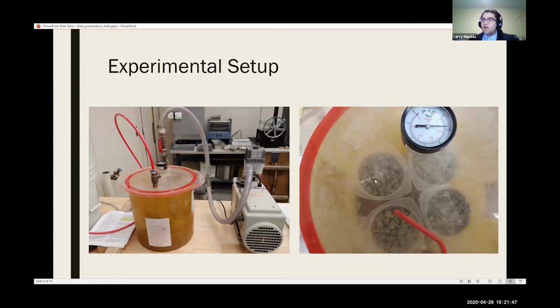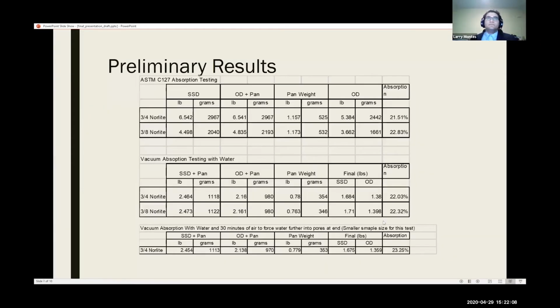After 3 hours, all the air trapped inside the aggregates has been removed. And at this point, the water was inserted into the chamber through this tube. And then after an hour of soaking, the rocks are removed and their weights are taken. So these are the final results of these experiments.